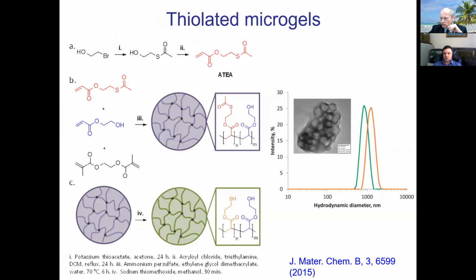And we've tried to use some slightly more complicated polymer chemistry. I'm saying slightly more complicated chemistry because it is from the viewpoint of pharmaceutical researchers who do like the simple one-stage reactions. So in this piece of work, what we have done, we designed a monomer with protected thiol groups. We converted it into microgel particles using conventional emulsional free radical polymerization. Then we deprotected the thiol groups and prepared the thiolated microgels.